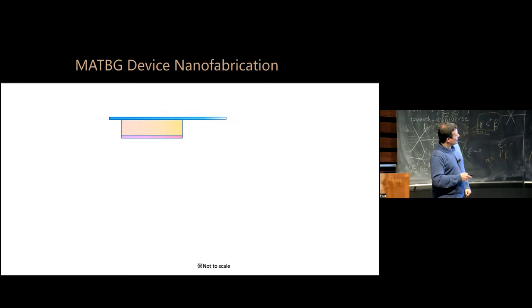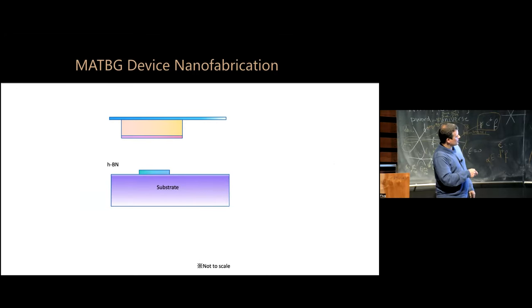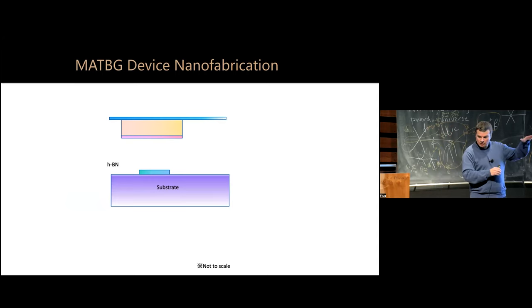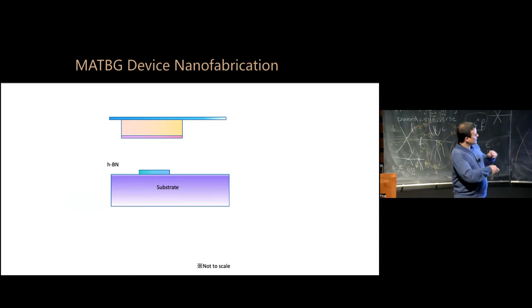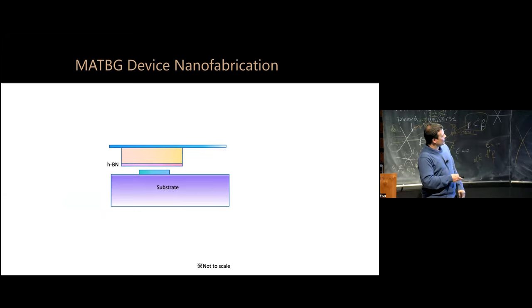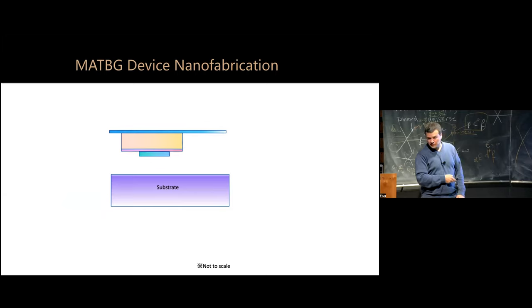So we start with a glass slide, transparent glass slide. It's almost as simple as the scotch tape, okay? Not quite, but almost. We have this glass slide and we have a sticky polymer, okay? Something that is sticky, similar to scotch tape, a little bit different. Then we bring a substrate which has hexagonal boron nitride. Remember, hexagonal boron nitride was this insulator. This is about 10 nanometers thick. We just want to use it as a substrate, put graphene on top. Okay? It's a high quality substrate. We pick it up with this sticky polymer. Just pick it up. Okay?